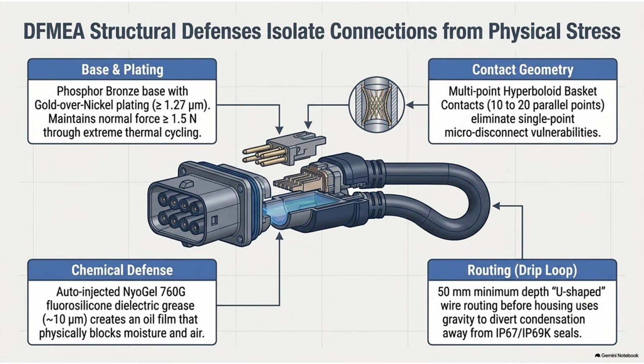Exactly. They eliminate the mechanical root cause, but they didn't stop at the base metal substrate. They fundamentally changed the surface plating too. We discussed how tin plating scrapes off and oxidizes into an insulating rust. The new specification demands a gold over nickel dual layer plating. Now, using gold makes obvious sense to me. Gold is highly conductive, and it is a noble metal, meaning it doesn't react with oxygen. It doesn't rust or tarnish.